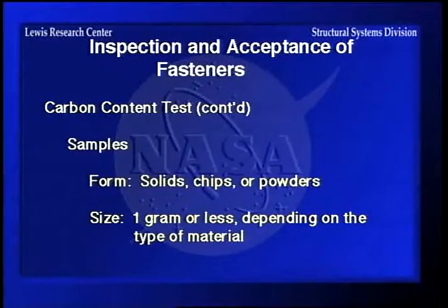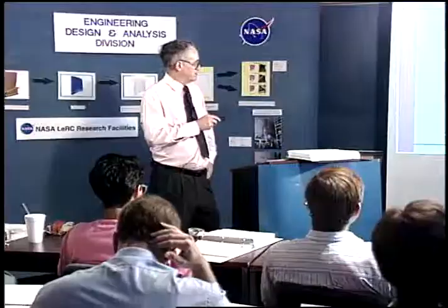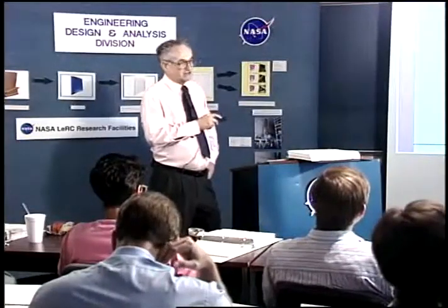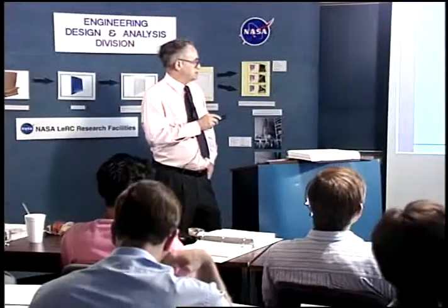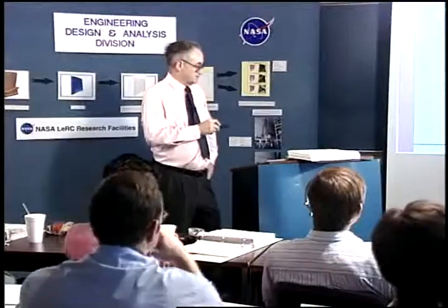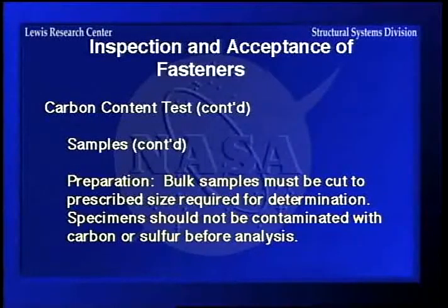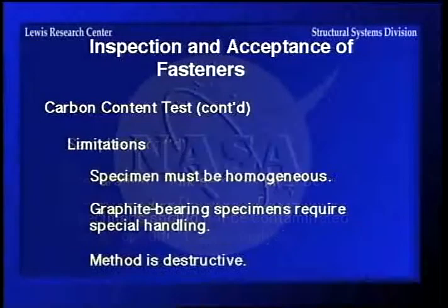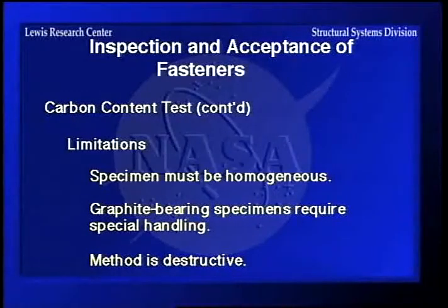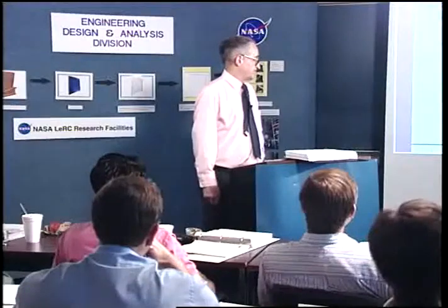The samples, here's one of the important things. You have to make sure that you know exactly how much weight you have in your sample in order to do the testing, because what you're looking at is the carbon per weight in it. And since it's such a small amount, the weight of the sample has to be accurate. The limitations on it also, the specimen must be homogeneous. In other words, I spoke of the decarburization. If you had, say, heavy content of carbon in the surface of the thing, due to the way it was heat treated, then you would get an erroneous reading. It would show that it had a higher carbon content than it really had throughout.